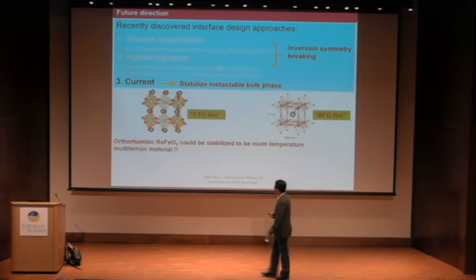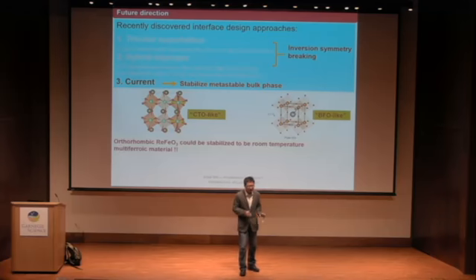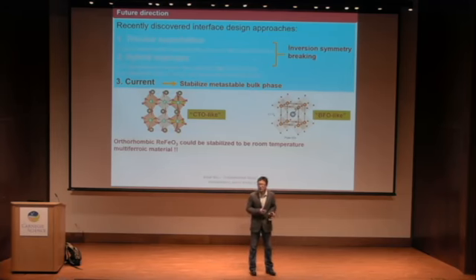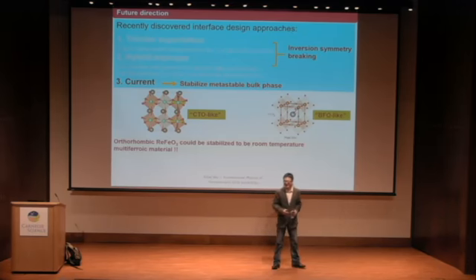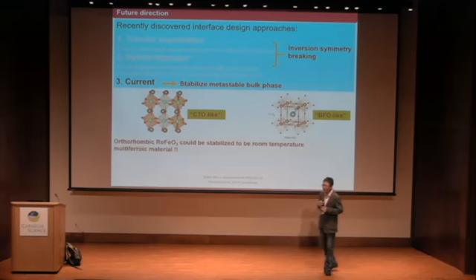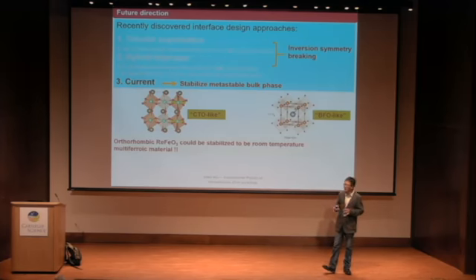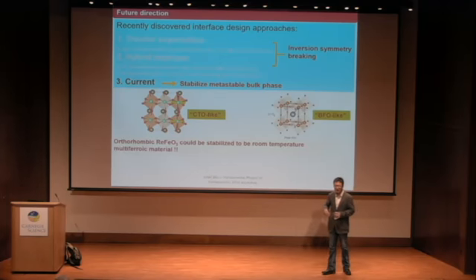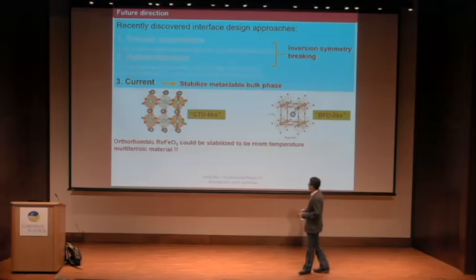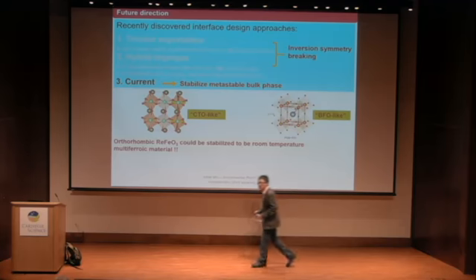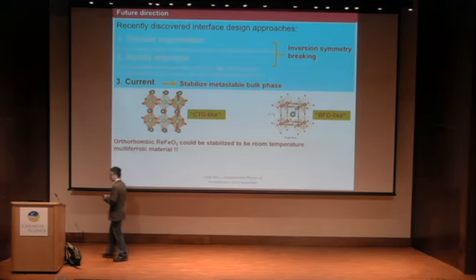For future work, the example we demonstrated is very interesting. However, we know the polarization hasn't exceeded that of bismuth ferrite yet — it's not huge. For future work, I think it's important to turn to other rare earth iron oxides. For example, many orthorhombic compounds have pretty high transition temperatures but no ferroelectricity. Maybe we can turn these materials into room temperature multiferroics.